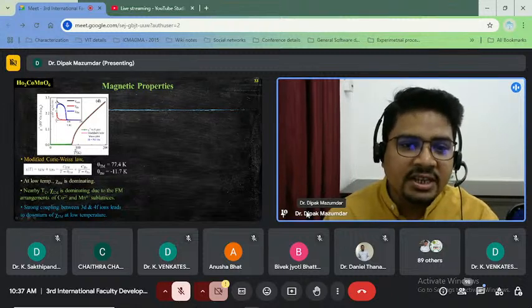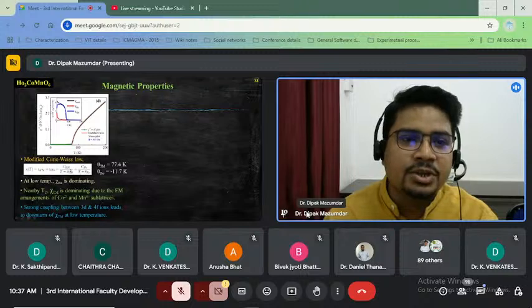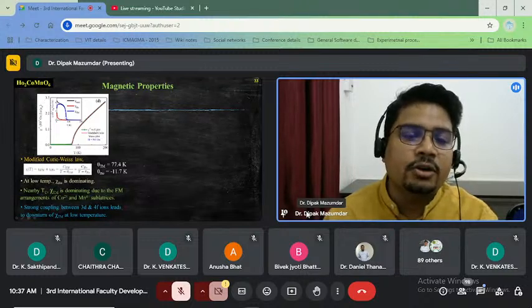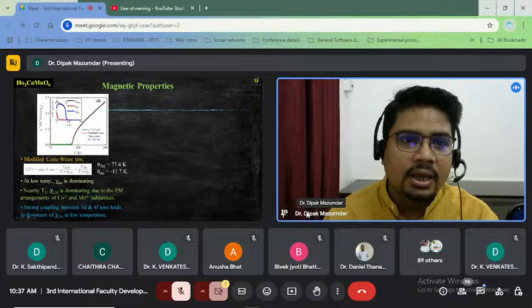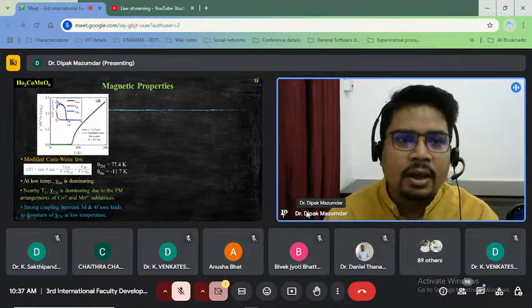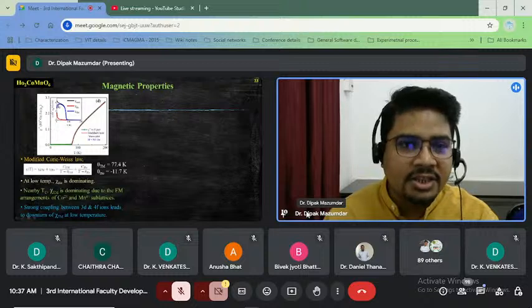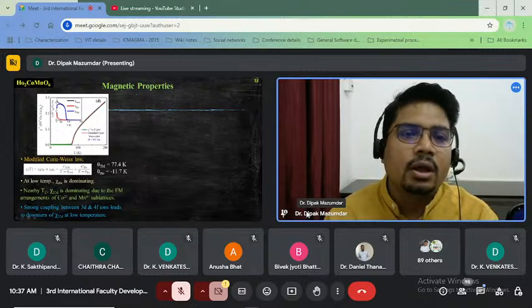From this fitting data and the extracted parameters, we can estimate the contribution of magnetic ions. You can see the black curve is the total magnetization data, the blue one is for transition metal ions, and the red one is for the rare earth ions.